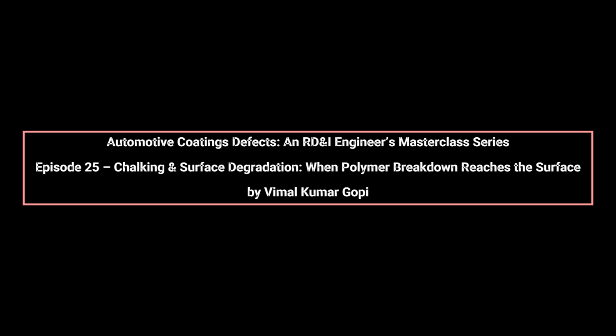From a testing perspective, chalking is evaluated using long-term weathering tests, such as xenon arc exposure combined with visual and weight loss measurements. OEMs correlate these results with outdoor exposure in severe climates. Systems that chalk prematurely in lab testing rarely survive real-world conditions. Troubleshooting chalking complaints focuses on exposure history, additive depletion, and cure verification. Additive adjustment is a formulation-level decision and not a plant-level fix. Process deviations that accelerate chalking include insufficient bake, incorrect film build, and contamination that interferes with UV stabilizers.